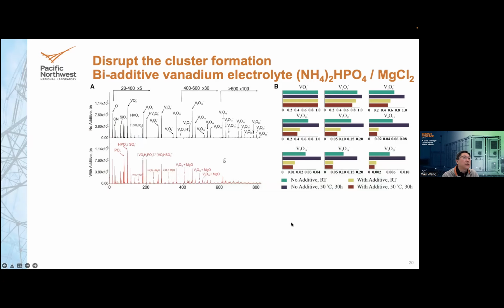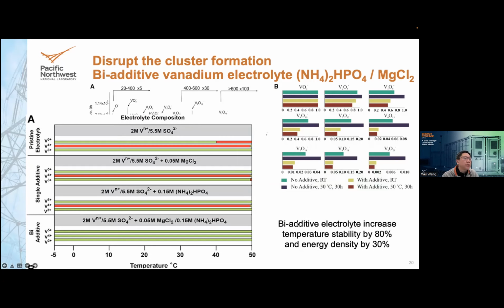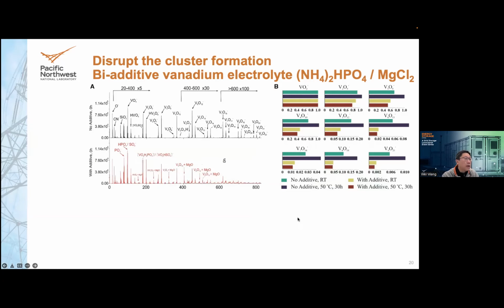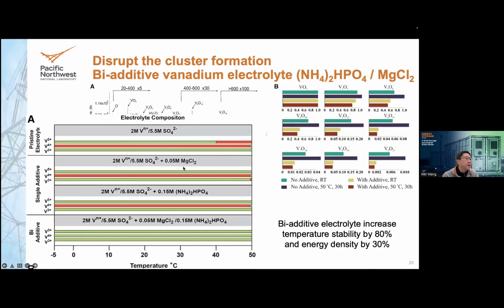I'll skip this one. Basically, this shows those higher order vanadium oxides. When you add the additive, there is a lot less of those species. Therefore, you can prevent them from further aggregating and becoming solid and precipitating out. And this is the performance of this electrolyte compared with different valence.